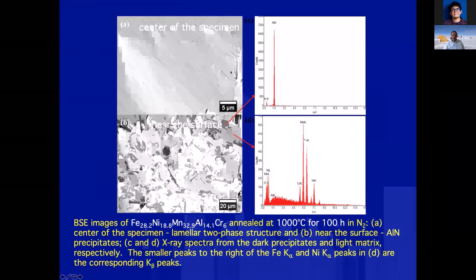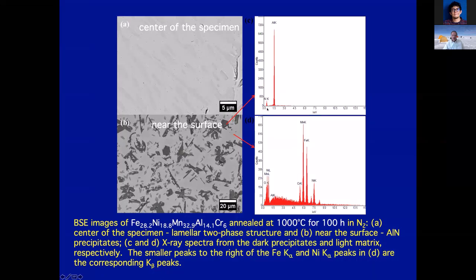So another thing we've done is actually nitride the material. We did this to both the chromium doped material and without chromium. And this is after we've nitrided the material. So this is at the center of the specimen where nothing much has changed. We've got this similar structure. But near the surface, we've actually got quite a different microstructure. We've got these dark particles, which if you do EDS on, turn out to be aluminum nitride. And if you look at the matrix between those particles, there's actually no aluminum. So the nitriding basically sucks all the aluminum out of the matrix and forms these nitrides.